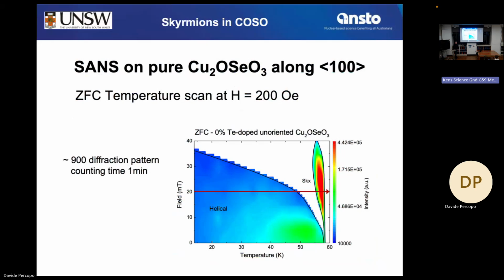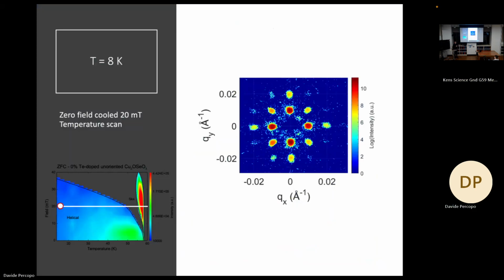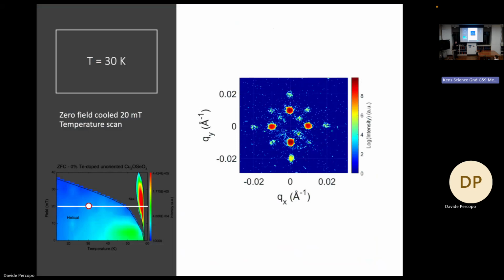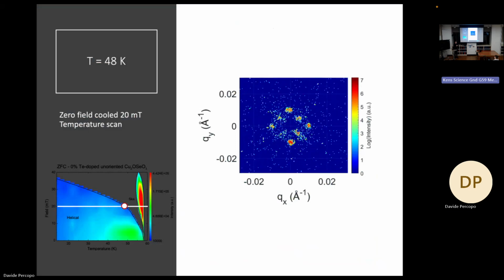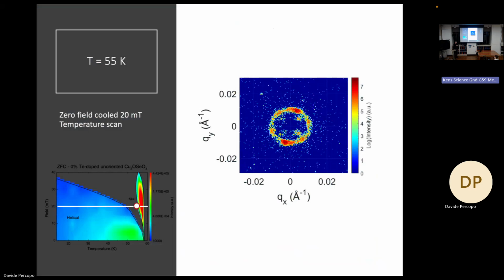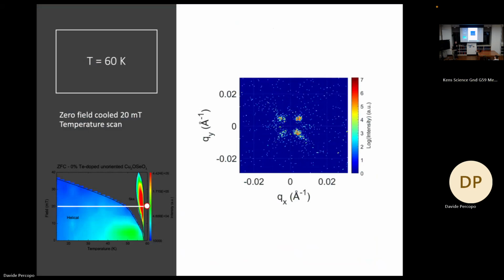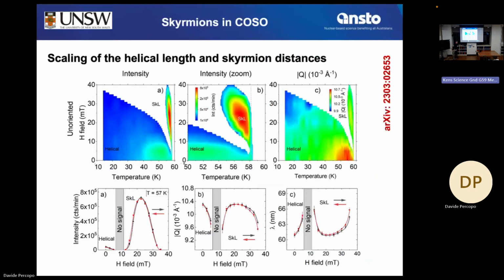So next I show you the raw data as a kind of video. It starts from the helical phase. In that case, 2 domains at 90 degrees. So we expect 4 sharp Bragg peaks. And actually, since the crystal is of such good quality, also higher orders. So 8 and so on. Then we enter the skyrmion phase and then we see 6 peaks. So this is how it looks like. The helical phase becomes weaker and weaker, disappears for a moment, and now the skyrmion ring shows up. So this is the result.